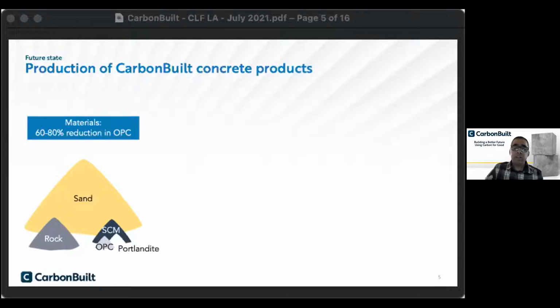I should note this is not a one-for-one replacement with cement. So I said we reduced Portland cement by 70%. We're adding in some Portlandite, but the bulk of the gap is filled by adding fly ash or slag, whatever low-cost waste materials the producer has access to today. And this is really what drives the cost reduction and the reduction in embodied carbon, particularly if we're using commercially available Portlandite. So that's the change on the material side of things.